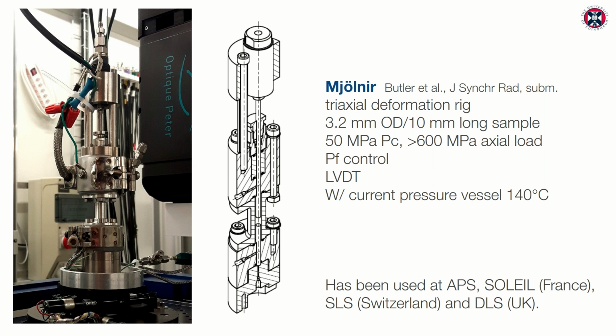Roughly we can establish a 50 MPa confining pressure in this cell at room temperature, and exert over 600 MPa axial load. We can control the pore fluid pressure. This cell is also equipped with an LVDT, which is not shown in this image because we've only added it last December. And with the current pressure vessel, although not at these pressures here, we can reach 140 degrees Celsius. You see the same band heaters here mounted to that rig.